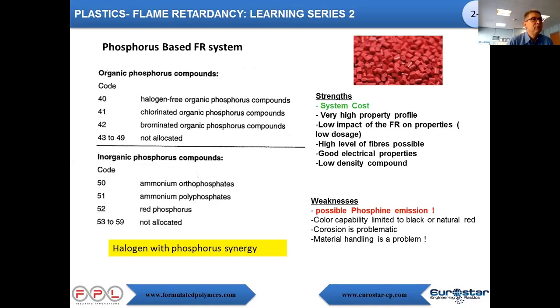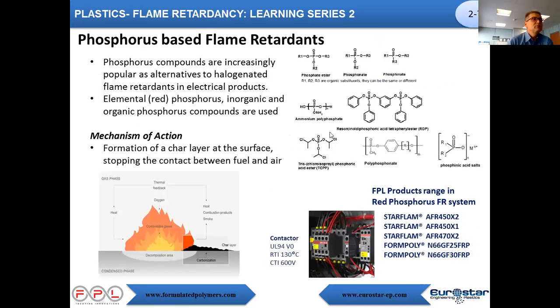But the novelty over the last years is the use of halogen-free phosphorus compounds. There we are using molecules which are always phosphorus derivatives. So you see in all those molecules phosphorus atoms, no more chlorine, no more nitrogen as in melamine. This is one of the best ways to replace halogenated formulations when you cannot use them anymore and you need some stiffness. And for example, the color is white, so you cannot use red phosphorus. So these ones are really very effective.